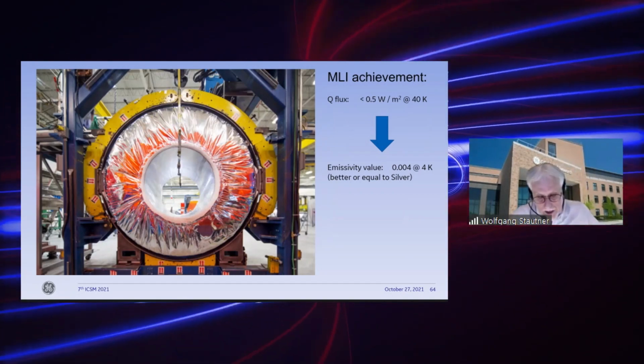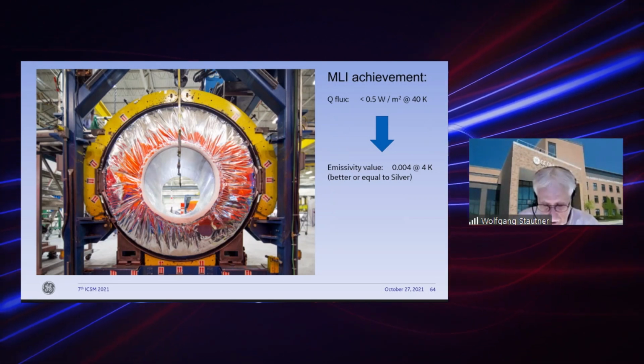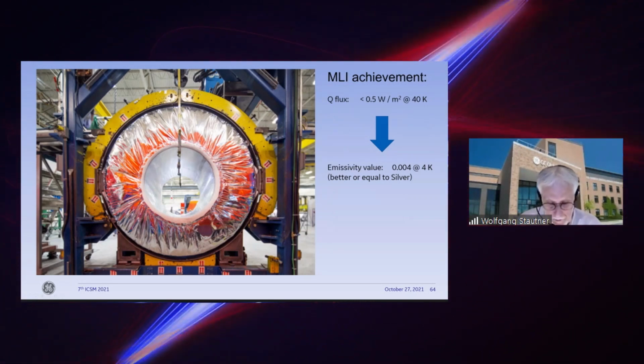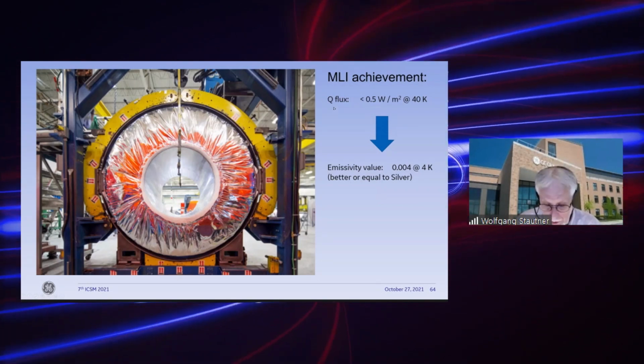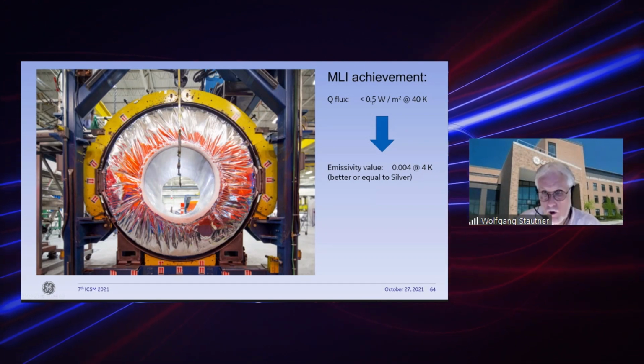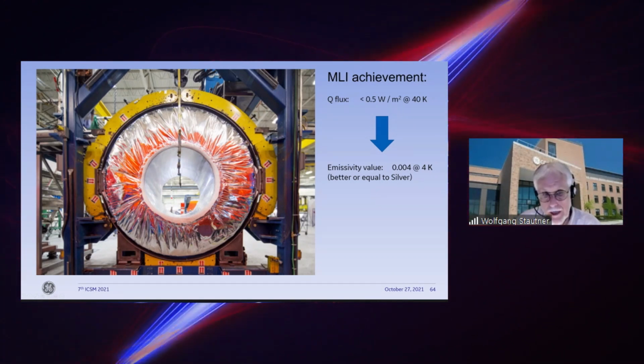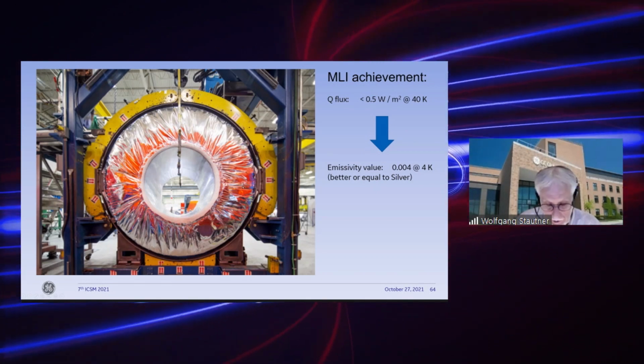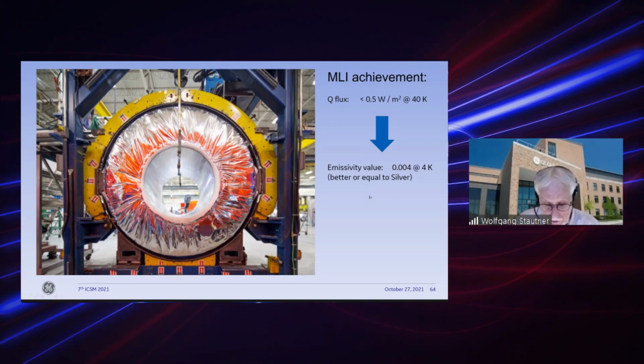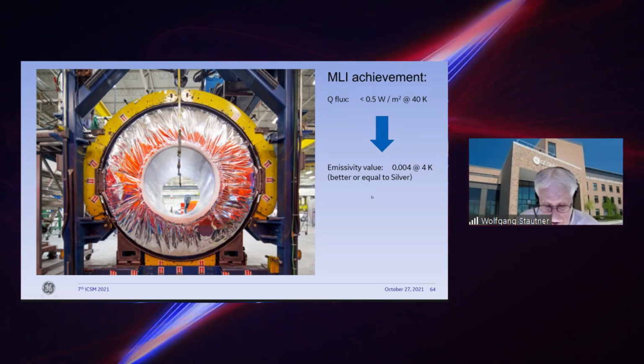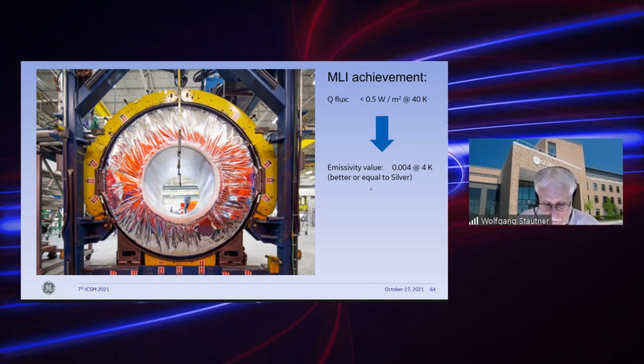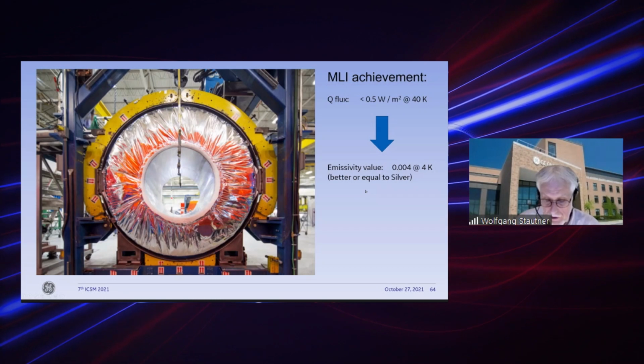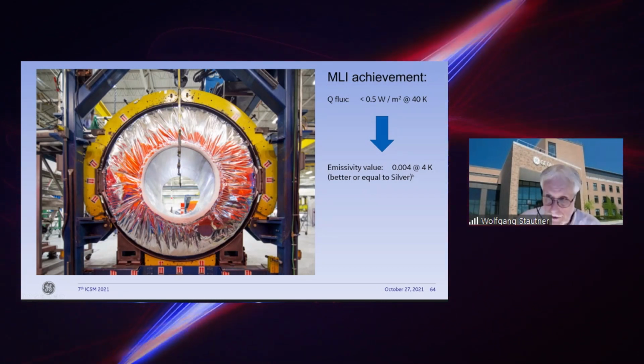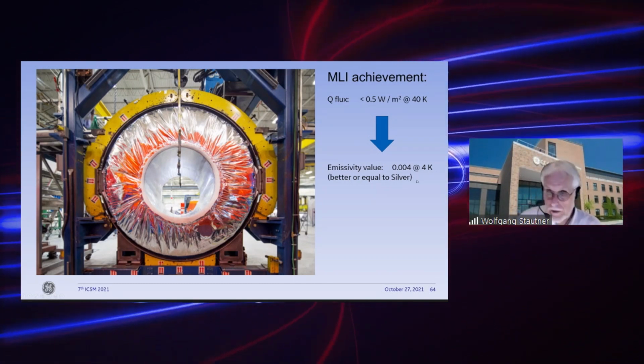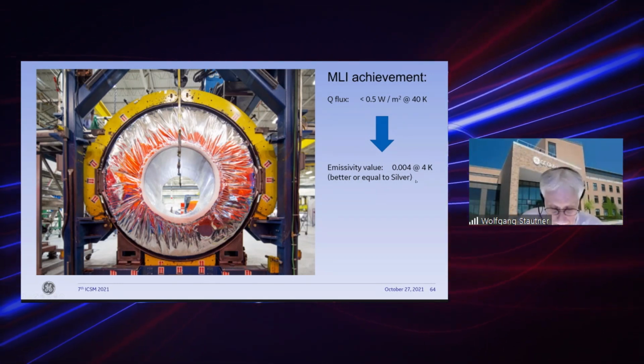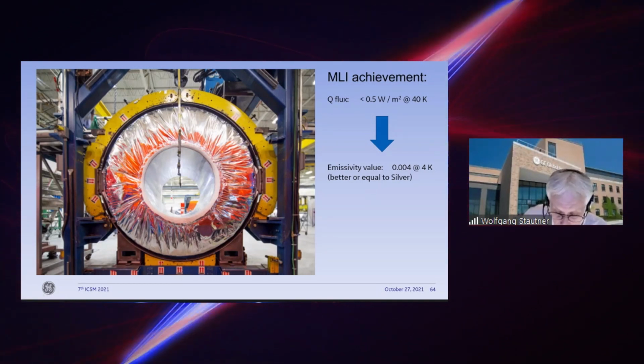So this slide is important as well. It shows an MRI magnet during assembly before closing it up, but note the big improvement is the foil performance here. We are now shielding with achievable heat fluxes down to less than 0.5 watts per square meter. So that has about 15 square meters in total surface. And for 4K surfaces, we now have a single layer foil that's wrapped around the helium tank that has an emissivity factor of 0.004. That is what can be achieved now. It's a recent achievement. It's better or even equal to silver. It's a huge improvement thanks to recent advances in 4K foil technology.